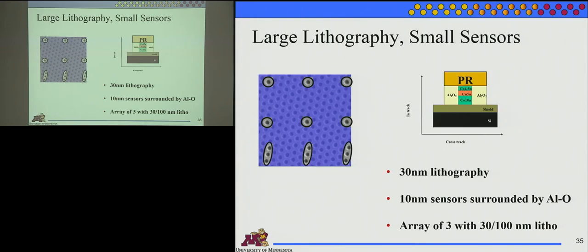And that 31 had 5%. So our wires have 18% MR, magnetoresistance. And when you put a blob that's 30 nanometers on top of our structure and mill away everything around it, you're left with a 10 nanometer wire that's already in aluminum oxide. So the sidewall damage is happening out here where you don't care about it. Then you can put down your exchange bias, lift that off, put a shield on, and you have a sensor.